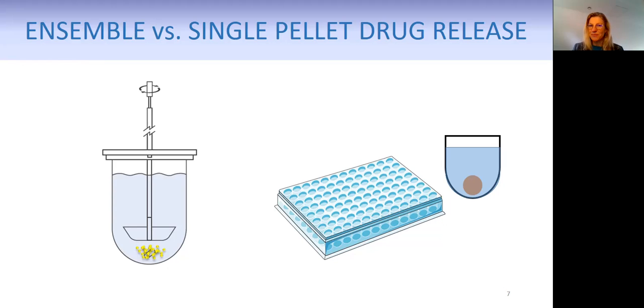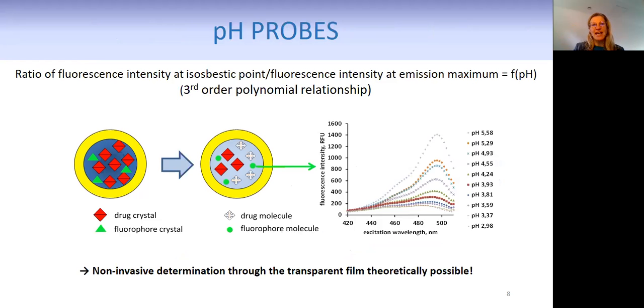And we combined these single pellet drug release studies with an observation of how the pH is changing within the pellet core. To do that, we had to probe the pH in the pellet core. This has been done with pH sensitive fluorescence probes. The fluorophores we used were incorporated in the core material. So we made another batch of pellets, adding BCECF dextran and Oregon green. Upon contact with the dissolution medium, these fluorophores, which are very soluble in water, dissolved and, depending on the pH, emitted a different intensity of fluorescence at specific wavelengths.